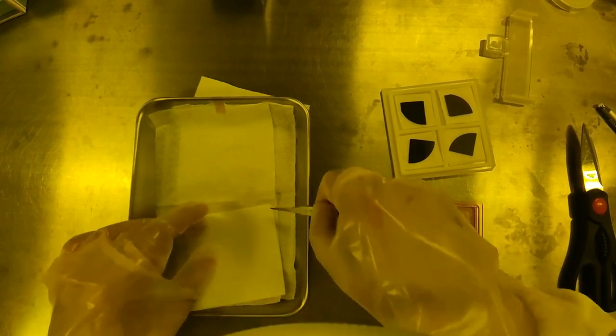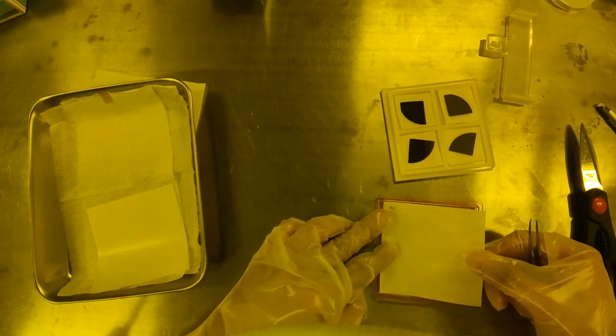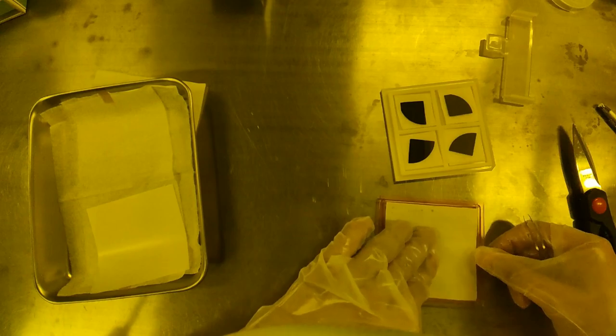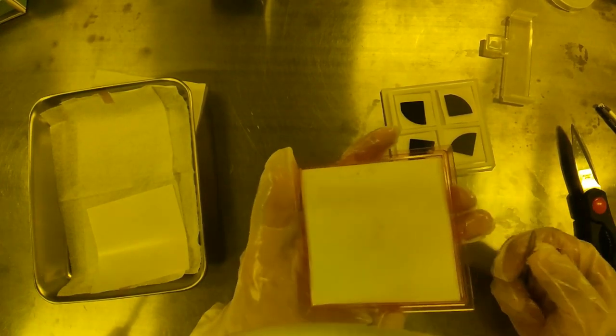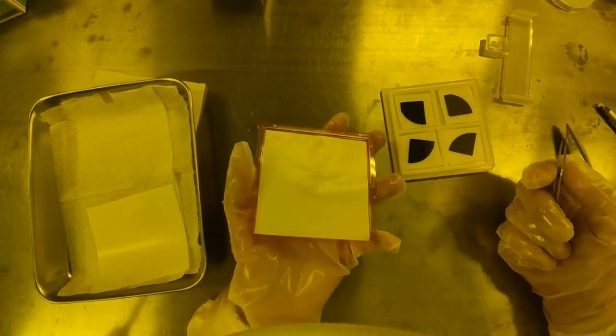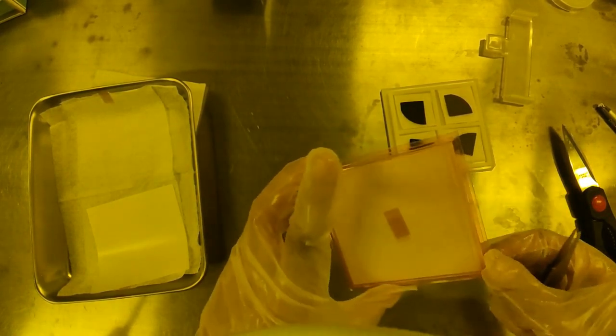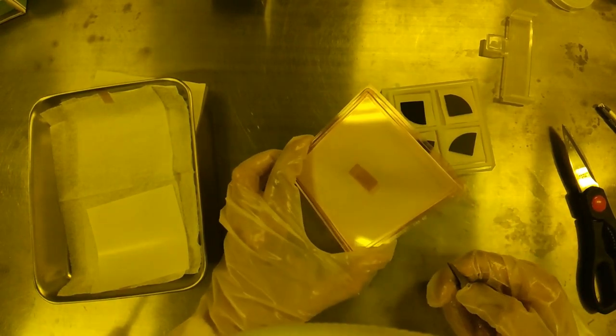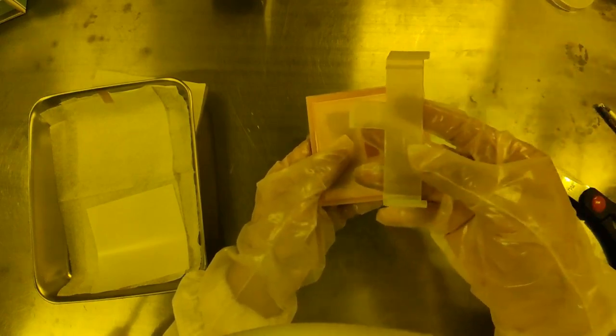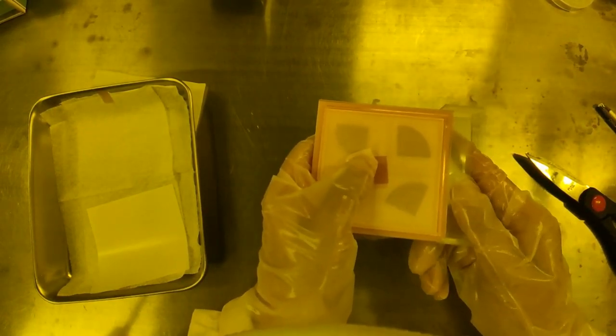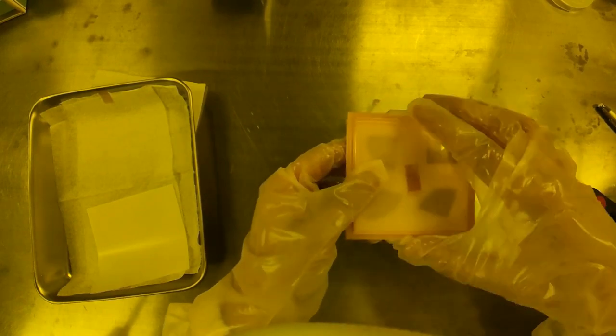You just take some tape. This is Kapton tape. We use it because it doesn't really leave traces when you remove it. But, well, it doesn't matter. You can use anything. So, just make a loop out of the tape like this. And add... It is essentially a cooking paper. It's a waxed small paper. And you just add it to the top. See? And this side is waxed, so no glue that you apply to the wafers or the photoresist, which essentially is also a glue, polymer glue, it will not stick to the top, giving you a good transportation medium. And to clip it, there's a clip like this. Just put it over the side. And you clip it. That's it.